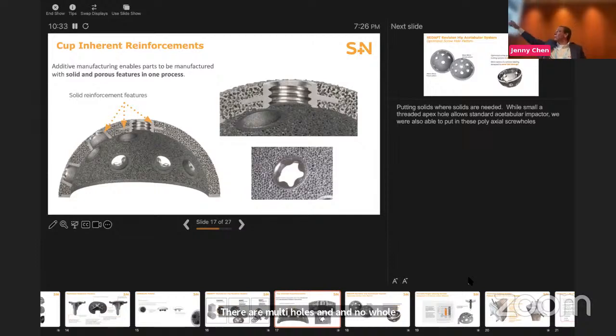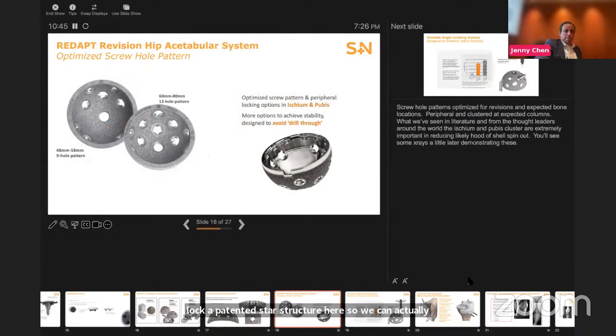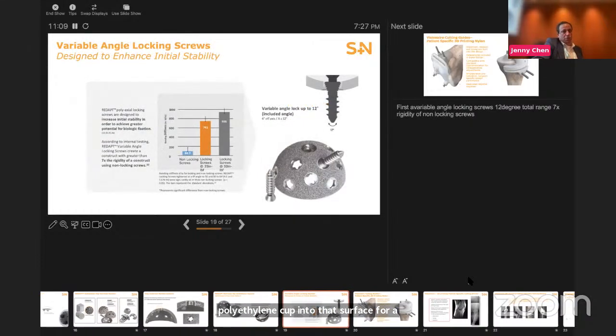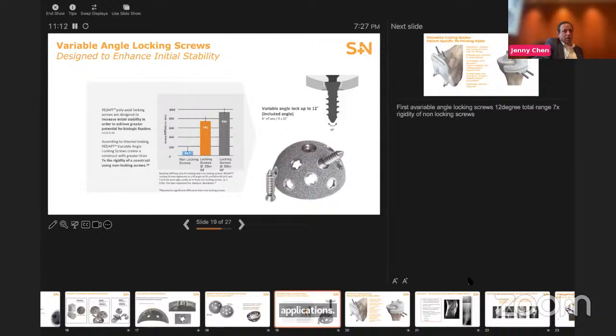A patented star structure here is that we can actually lock with a screw the acetabular cup into a revision type of situation. And again, we can either have it fully 3D printed and porous through and through, where a surgeon will cement into that, or polar cup, or we can actually go in and machine that surface and put an Oxinium cup or a polyethylene cup into that surface for dual mobility applications. Here again, we test the screws and the strength, very rigid and very capable of locking the cup into the acetabulum.